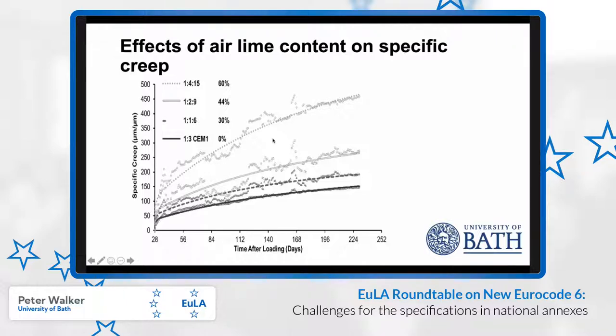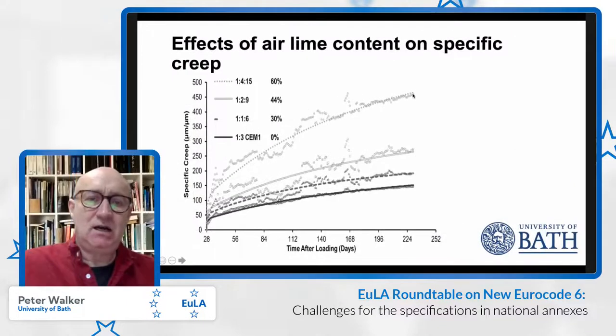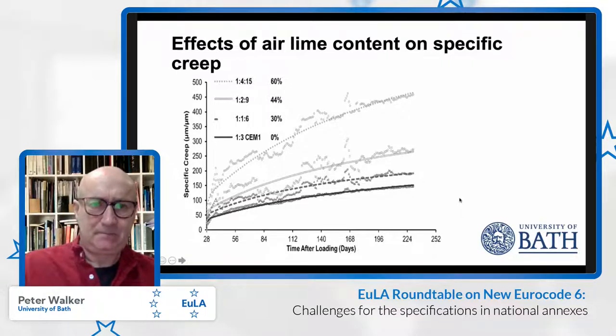But we can see here that the creep is higher as the strength of the material decreases, or indeed as the lime content increases. So going from the 1:3 CEM1 mix up to the 1:4:15 mix, we can see increasing creep movement with the increasing lime content.